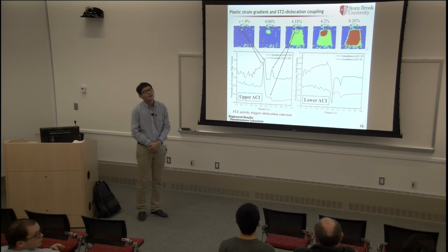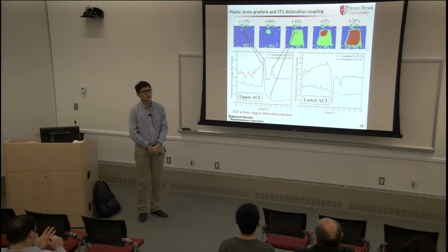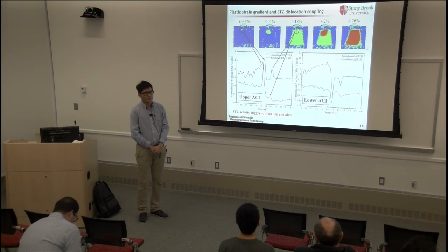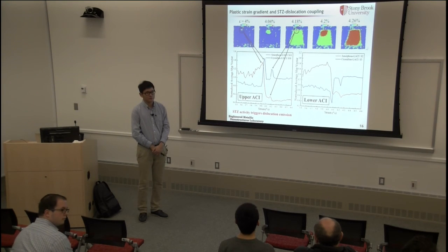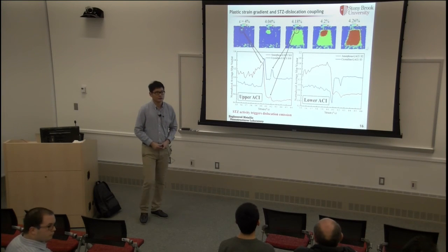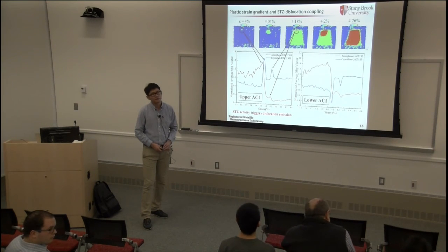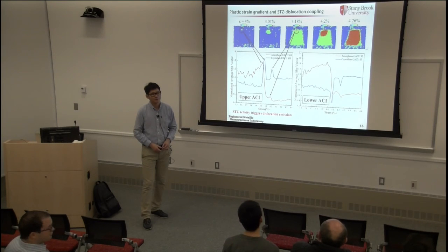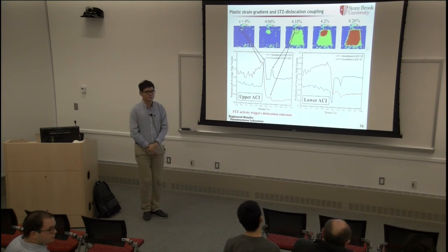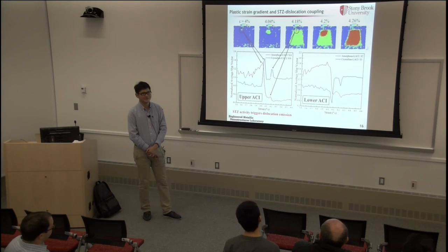So you should be aware that there's more behind that selection. The potentials, if you go through all the papers, have been experimentally validated to show that they can reproduce specific things that we care about. Things like stacking fault energies, the relationship between stable and unstable stacking fault energies through the generalized planar fault energy curves. These are all important aspects for reproducing more realistic mechanisms that have to do with these interfaces, so that all of the interfacial properties, energy specifically, are recreated by these various potentials.